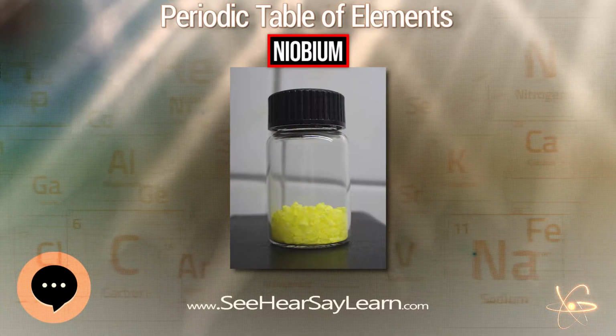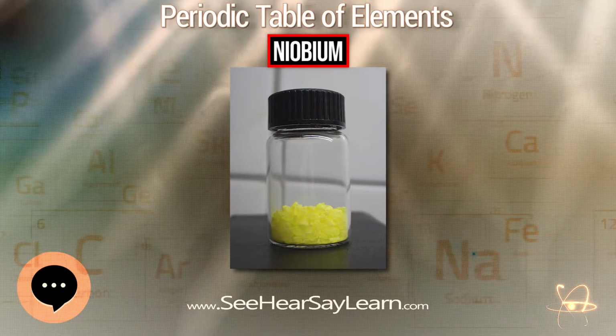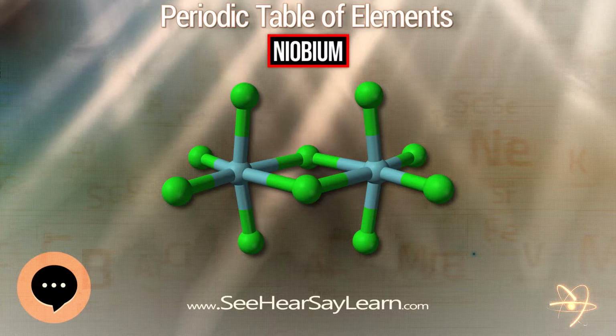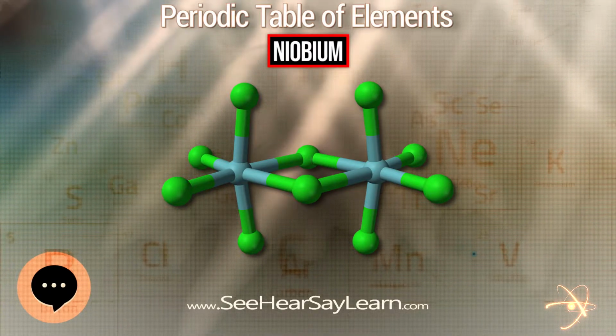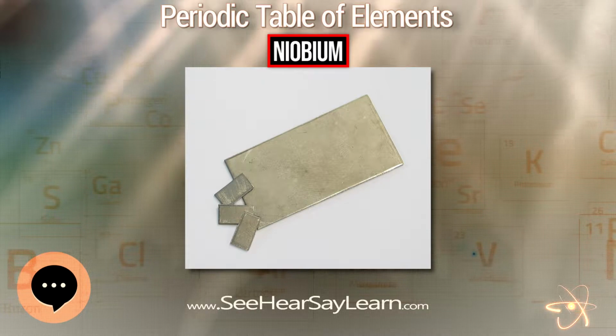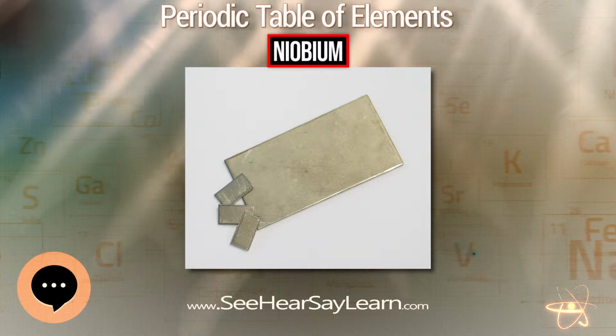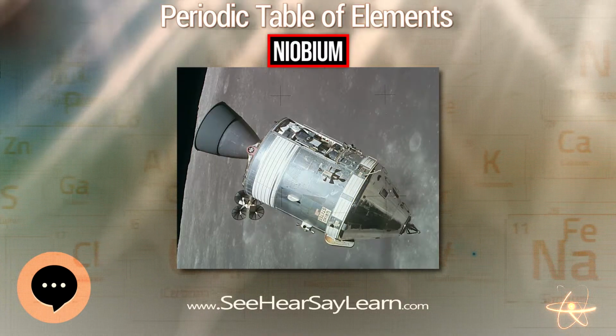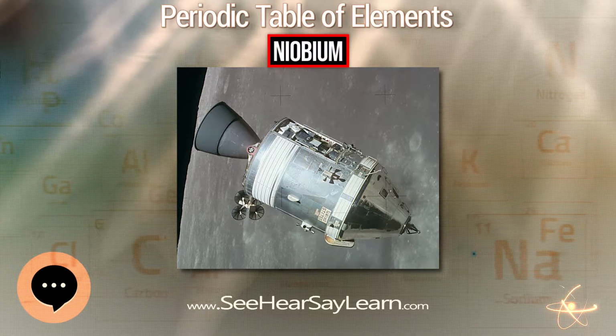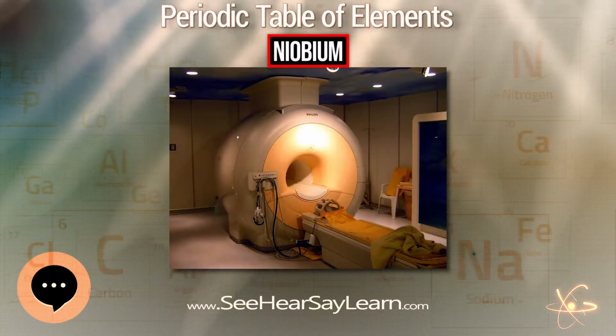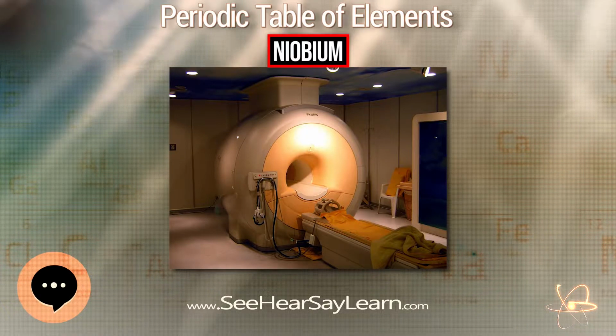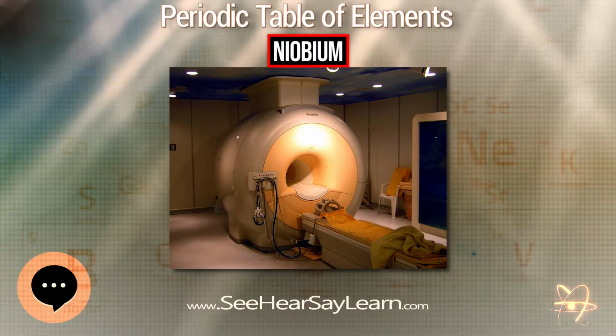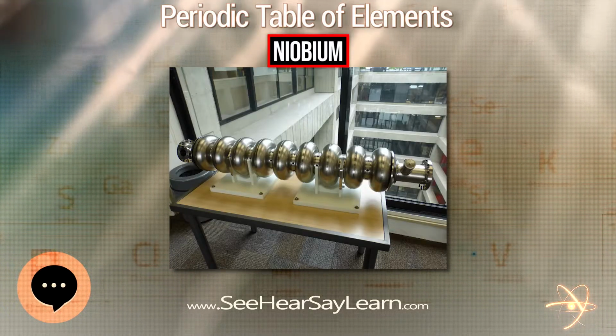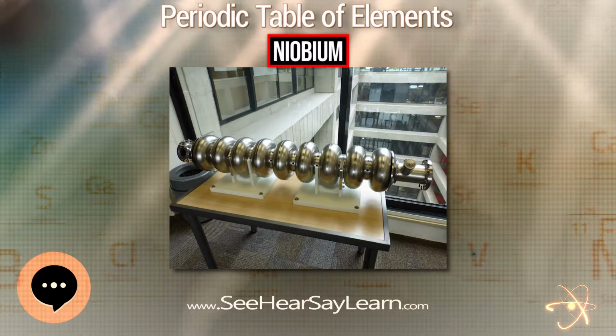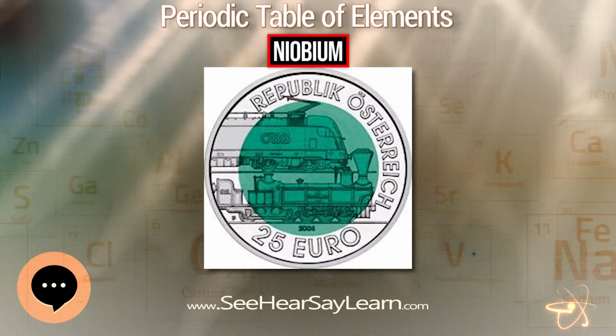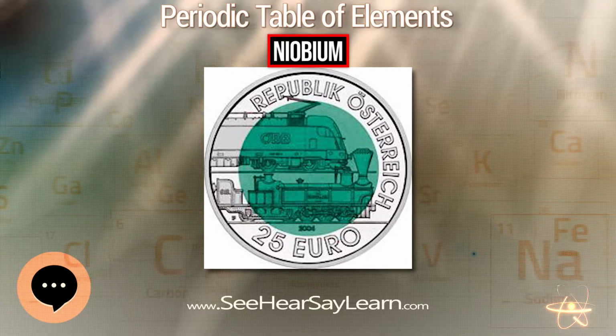Niobium becomes a superconductor at cryogenic temperatures. At atmospheric pressure, it has the highest critical temperature of the elemental superconductors at 9.2 K. Niobium has the greatest magnetic penetration depth of any element. In addition, it is one of the 3 elemental type II superconductors, along with vanadium and technetium. The superconductive properties are strongly dependent on the purity of the niobium metal. When very pure, it is comparatively soft and ductile, but impurities make it harder.